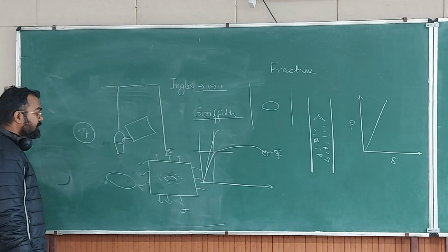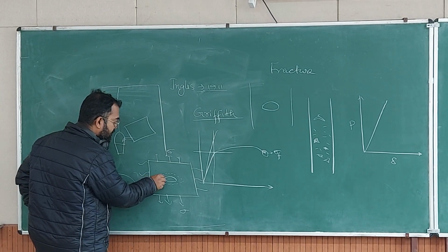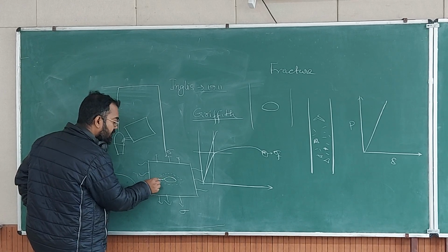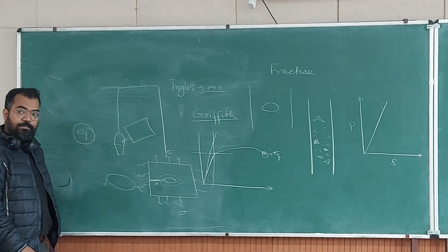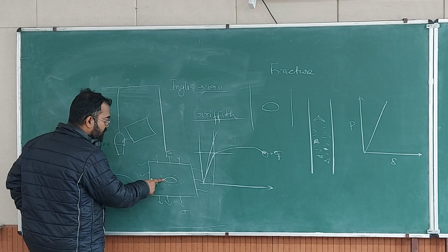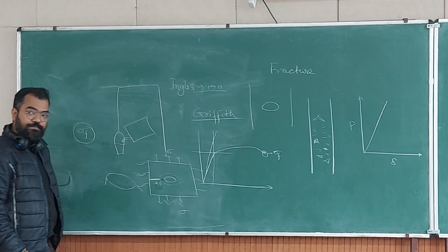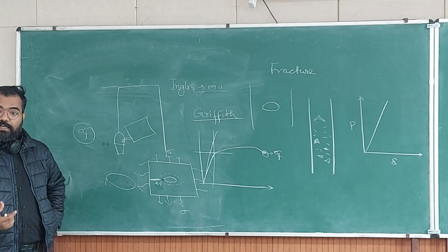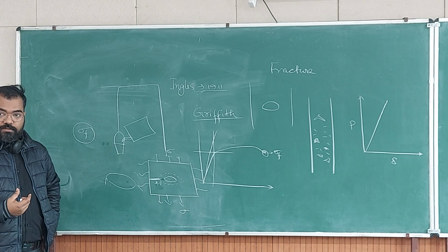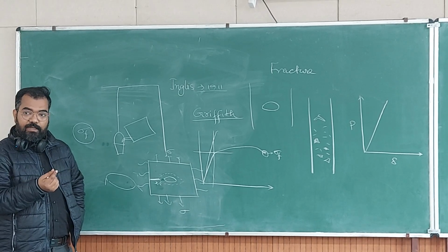You can just see that when the crack was here, on both sides you have, let us say, X millimeter of material which was intact, right? When the crack has grown by 2 millimeter, now you have only X minus 2 millimeter which is intact, right? So less material is intact. It is equivalent to having a wire which we are testing of a smaller diameter.